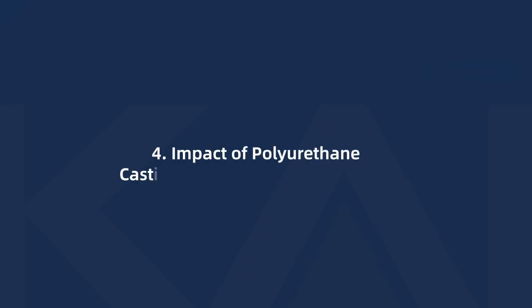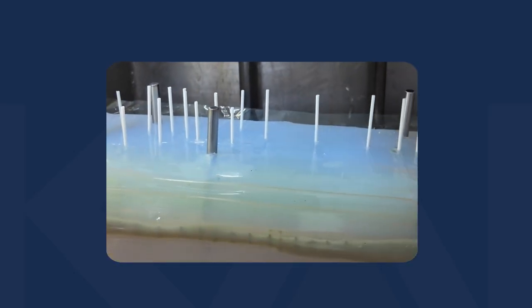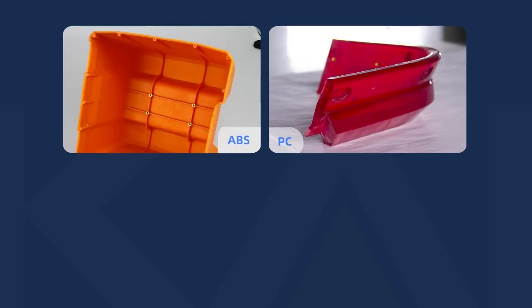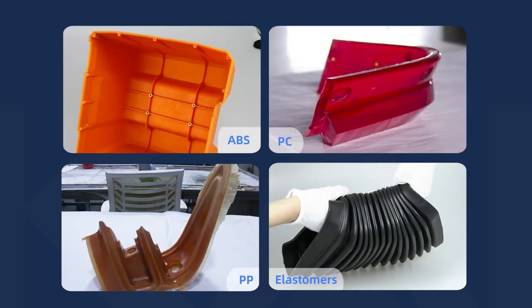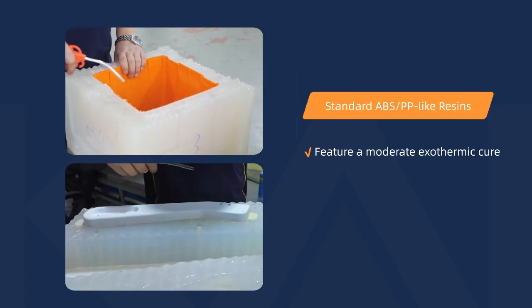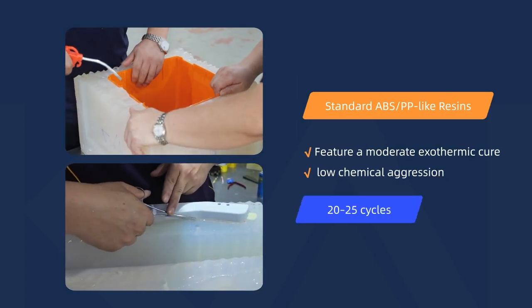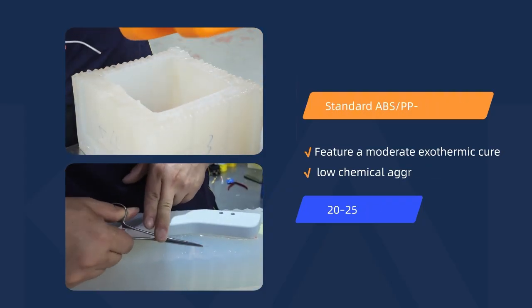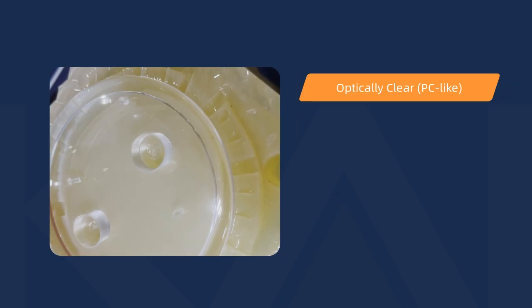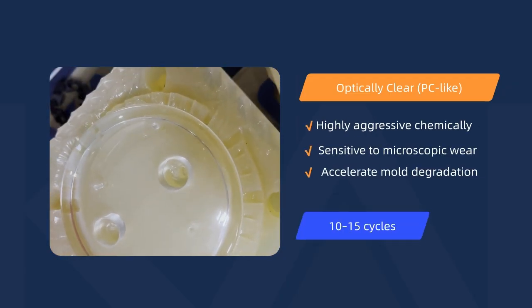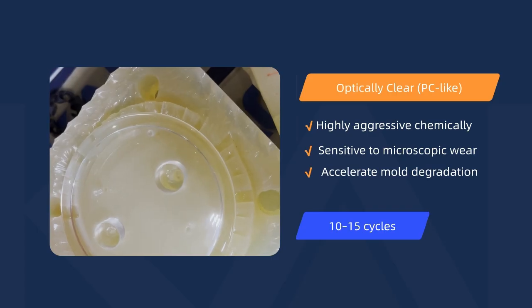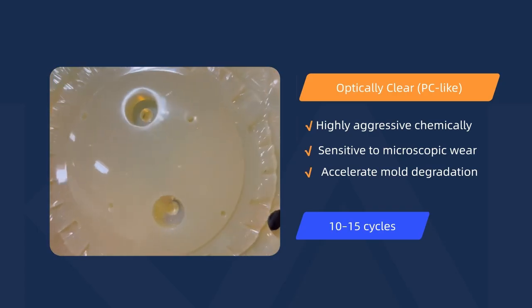4. Impact of polyurethane casting resins on tooling lifespan. Polyurethane (PU) casting supports a wide array of resins simulating ABS, PC, PP, and elastomers. However, resin selection directly governs silicone mold longevity. Standard ABS or PP-like resins feature a moderate exothermic cure and low chemical aggression, maximizing mold lifespan to 20 to 25 cycles. Optically clear, PC-like, and high-heat resins are highly aggressive chemically and sensitive to microscopic wear. They accelerate mold degradation, causing surface clouding that shortens tool life to 10 to 15 cycles.